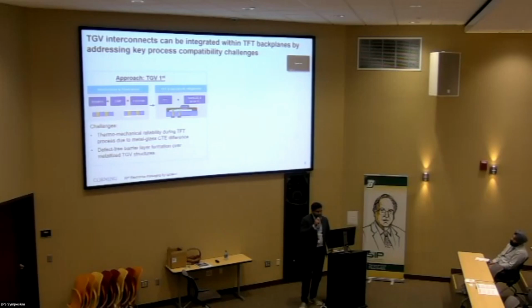So eventually when you subject this whole system to the LTPS fabrication or IGZO oxide TFT fabrication, you end up with huge stress because of the glass and metal CTE mismatch, and it creates a reliability challenge. So another way is, instead of fully filling the via, you can do conformal filling and then fill the remaining portion of the cavity with polymer or sol gel type of chemistries.